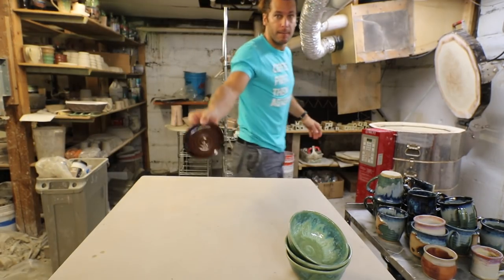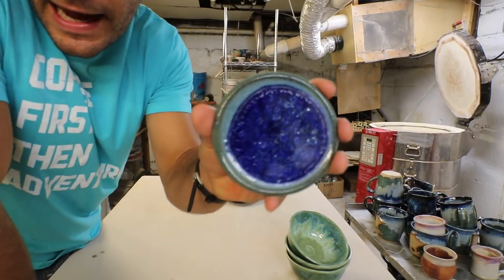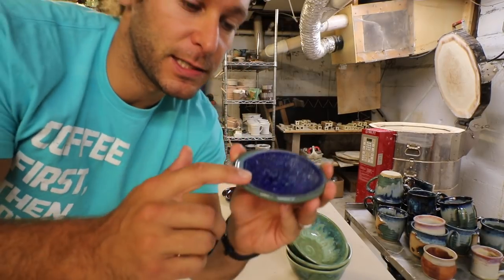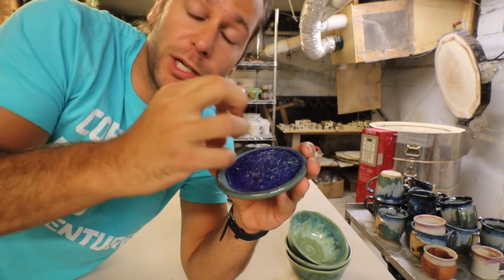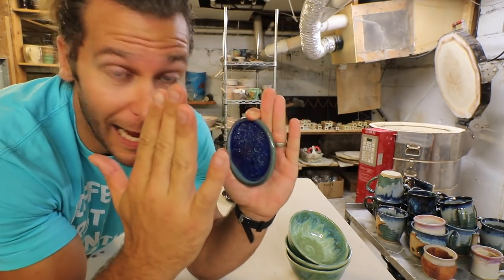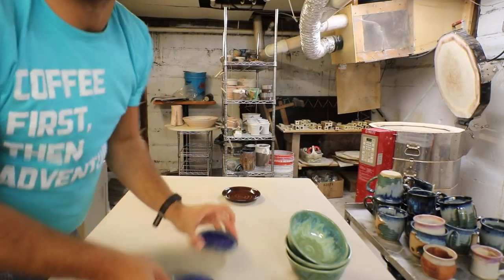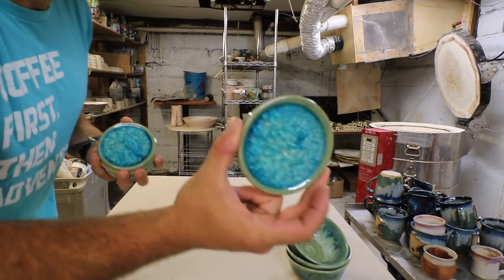This is a little plate for a berry bowl. Got a couple more of those glass coasters. If you've been trying to make these, I really think I've figured out the secret. Don't put too much glass in there, and make sure the edges are really gradual so they don't come straight up. When there's too much glass and the sides are holding the glass in, the shrinkage rates are different, so the glass will just crack the sides. All came out, none of them broke.